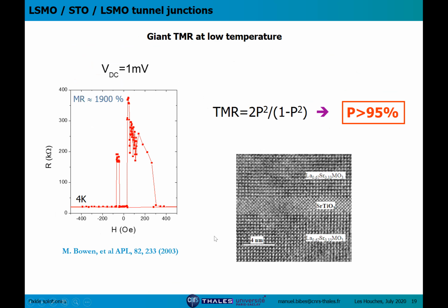Then we and others moved to integrate LSMO in tunnel junctions, basically combining two LSMO electrodes with a strontium titanate tunnel barrier. There were a number of results before the paper we published in 2003, already showing a large TMR. But in this one, we reached a very high value of TMR of almost 2000%. So this is, you can tell, much higher than the TMR obtained with transition metals, which was peaking at about 50%.